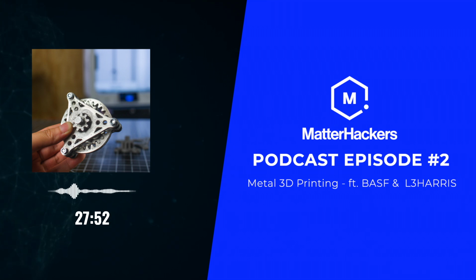So in manufacturing preparation, we will copy our design model, or preferably we link it back to the design model. So we have a manufacturing model linked to the design model. When you update the design model, the manufacturing model updates. That's been working out quite well for us. We prepare the model. We'll remove features that are best machined. So if you've got close tolerance holes or something like that, we'll remove those and put them in later. We add features to aid in printing, such as supports. We don't auto support. We generate most of those by hand because we found that to be more effective for us, especially for our small parts.